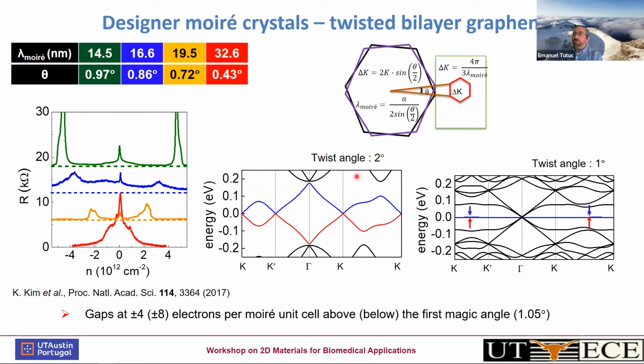It's very interesting. So what's shown here is the band structure in momentum space, and these points are the K points of the Brillouin zone of the moiré system, this thing right here. So these will be the Brillouin zone of the starting layers, and there is a Brillouin zone of the moiré system shown right here. And very interesting, there are angles where the electrons in these bands have very interesting properties. They slow down almost to a standstill, and when they do that, other interesting properties emerge, such as superconductivity, ferromagnetism, and also correlated insulator.